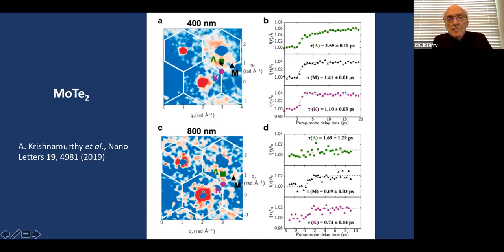So I believe T is what the old time band structure people called it, and then later they used U, and now we see it's called lambda. Okay. So anyway, here is the rise time of the strain in the crystal, which gives you a lifetime at the lambda point, at the M point, at the K point. That's for a 400 nanometer laser.